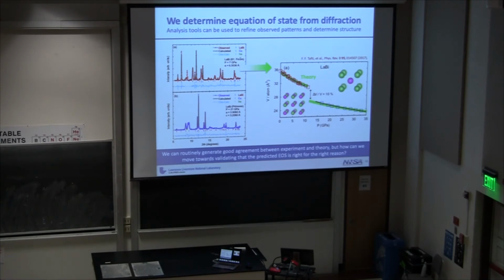There's a couple of advantages that you get from doing the synchrotron then. One is you have a lot of photons, so you can go through a lot of material, and you have high energy photons, so you can actually get through materials. Most of the time when you're sitting in your lab source and you've grown this beautiful single crystal that's 5 millimeters by 5 millimeters by a centimeter, you can't get X-rays through it. And your advisor doesn't want you to carve it into little tiny pieces to do transmission X-rays, so you do reflection. In our case, everything is small, so we do it in transmission. The high energies also take everything.